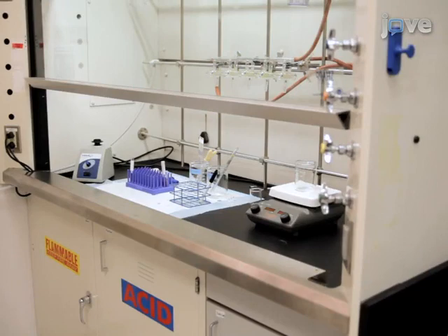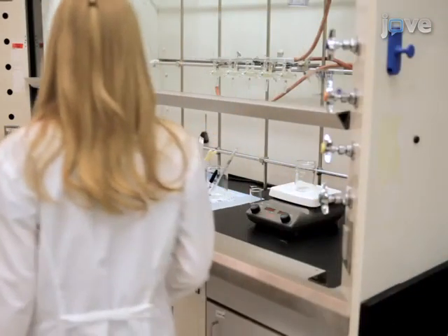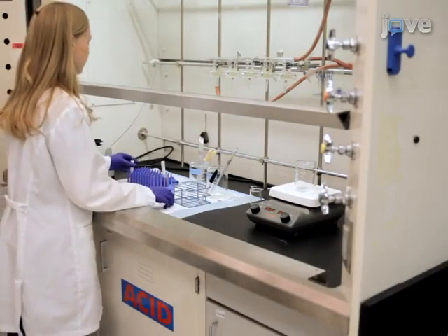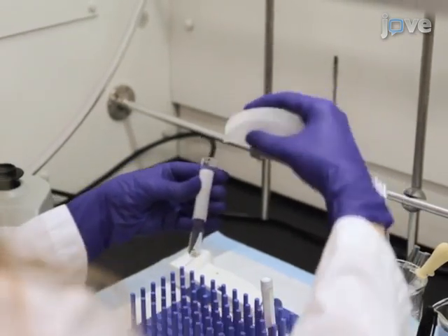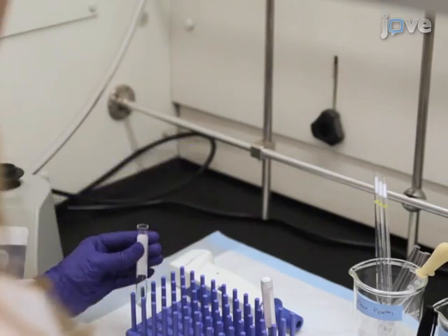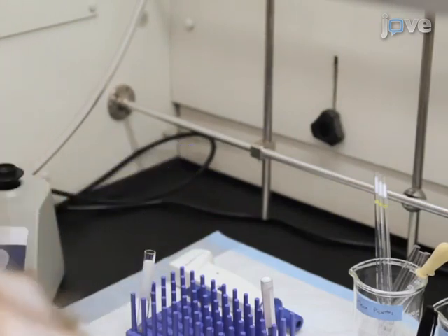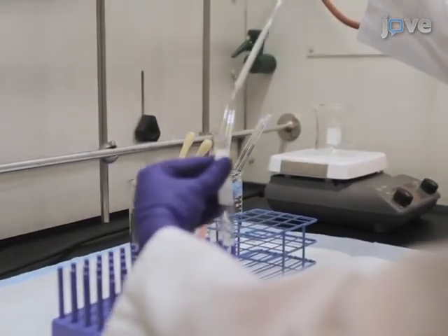To begin nanoparticle preparation, place approximately 100 mg of polylactic co-glycolic acid, also known as PLGA, into a 13 by 100 mm test tube. Then, using a glass serological pipette...